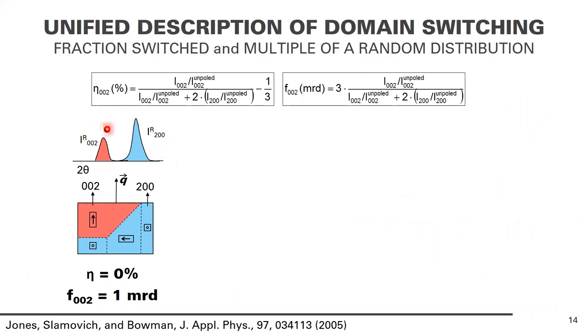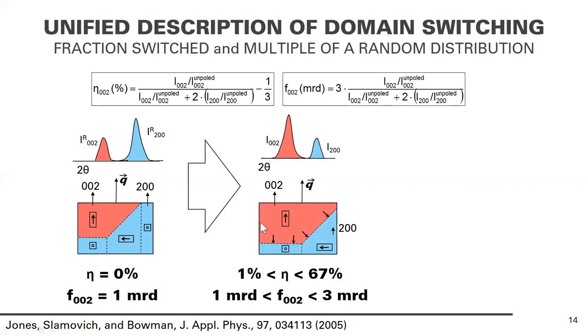All right, so what does this provide us? I showed this schematic earlier. This is for an initially unpoled sample. And here we can say that the degree of domain switched is zero, and that the pole density of the polar axis is one multiple of a random distribution. So it's equal to random. Okay. And if we apply some electric field, we can generate domain wall motion, and we can increase the volume fraction of the pink domain at the expense of the blue domain.